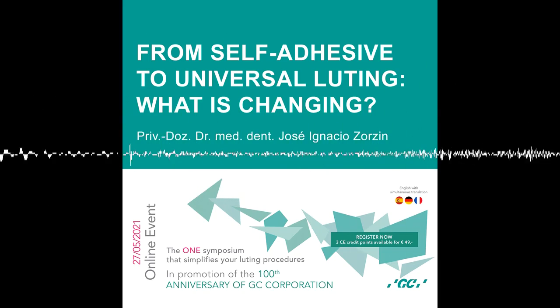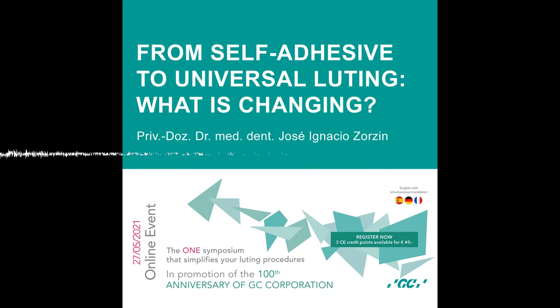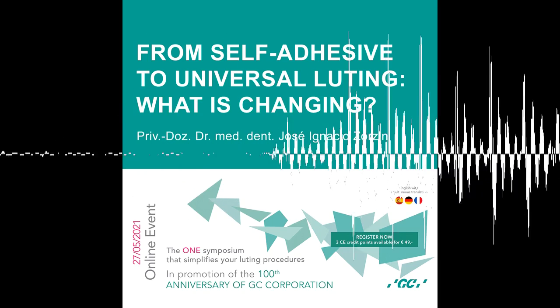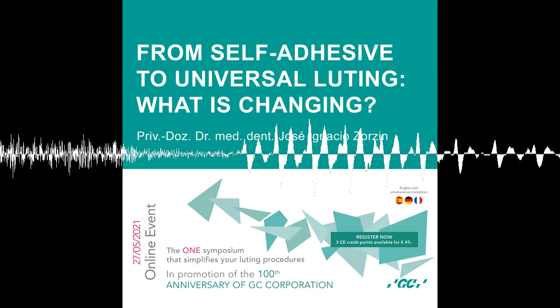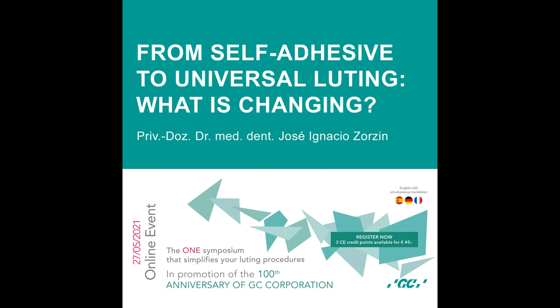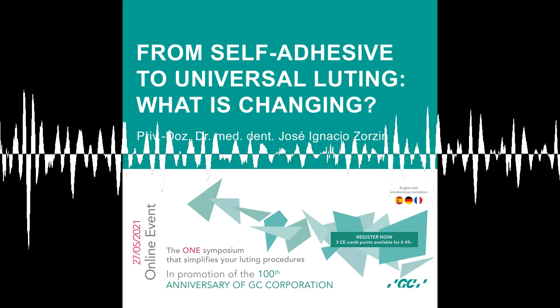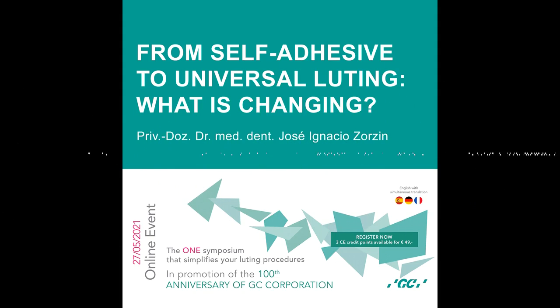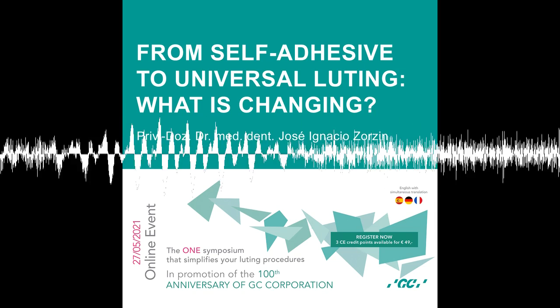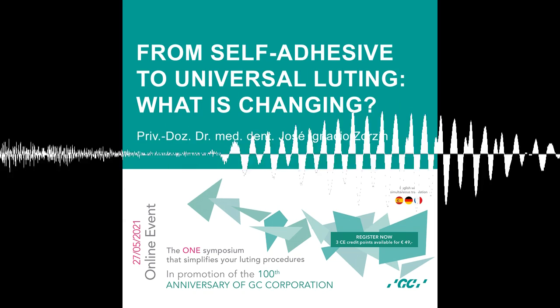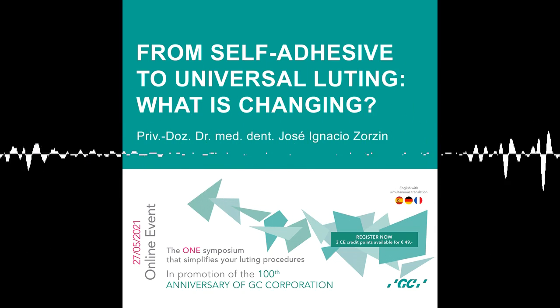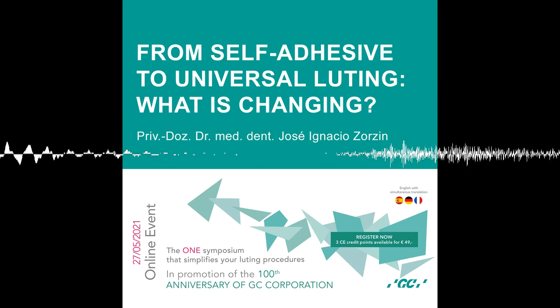And then we know from studies we did that with dual curing luting materials, always trying to cure them extra with light improves the conversion rate of luting resins and increases the strength of the luting. So whenever possible, do a dual light curing. This depends on many factors, on the thickness of the restoration, on the translucency of the restoration, and if you can really go for a dual cure, just do it. Do it because it will have better results in the long term.